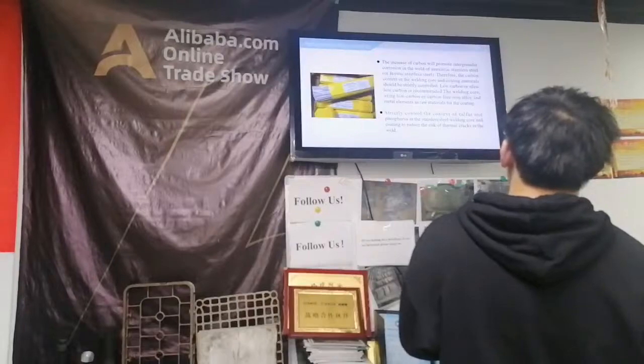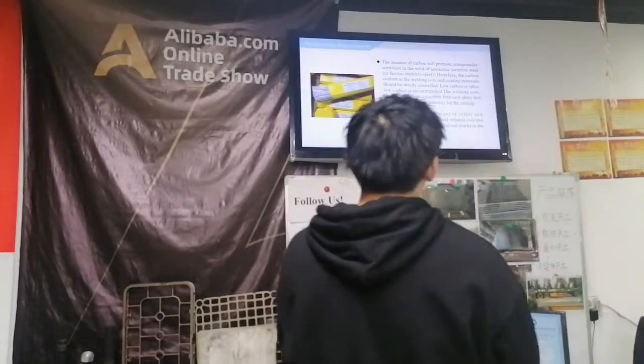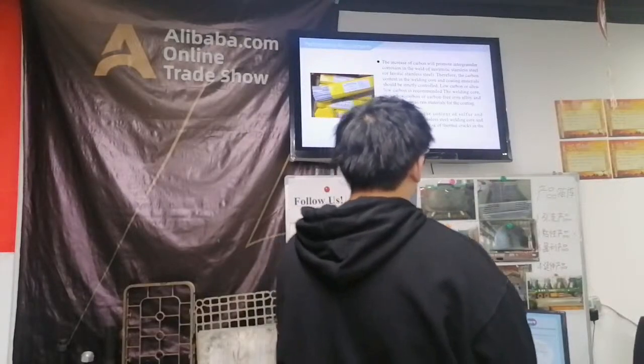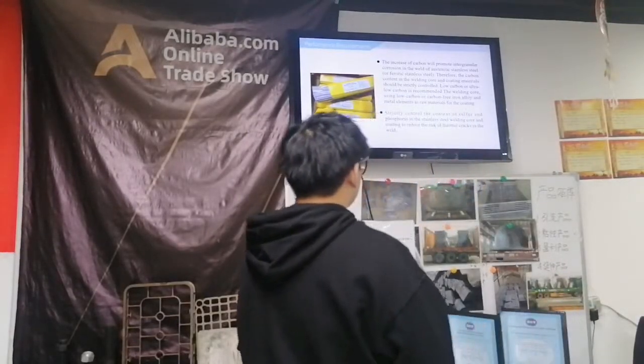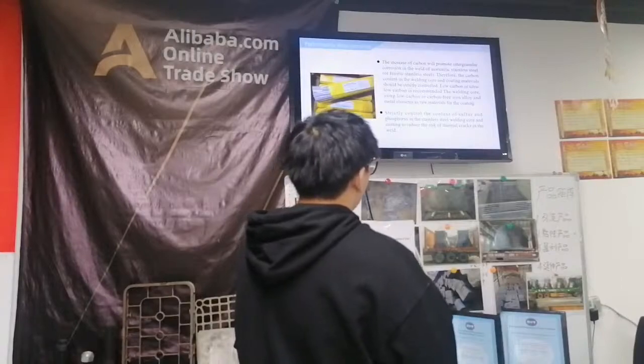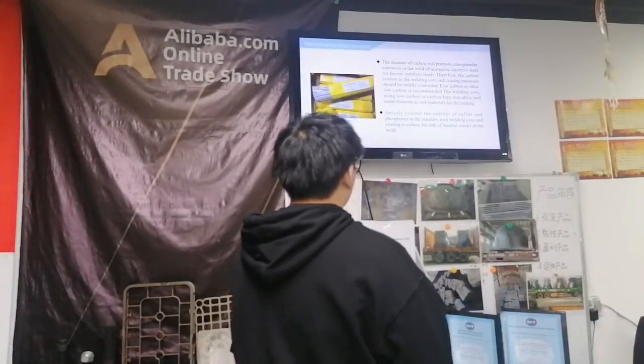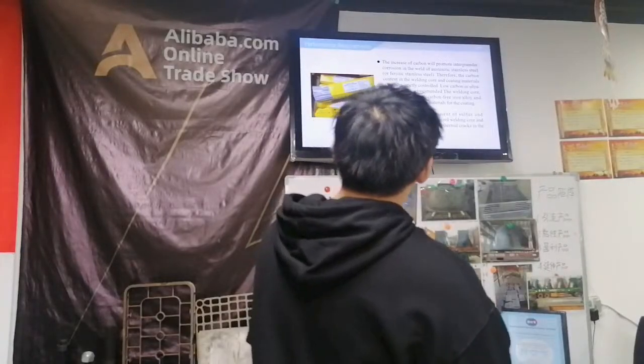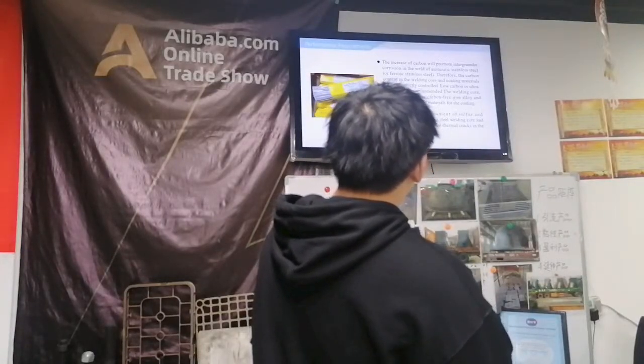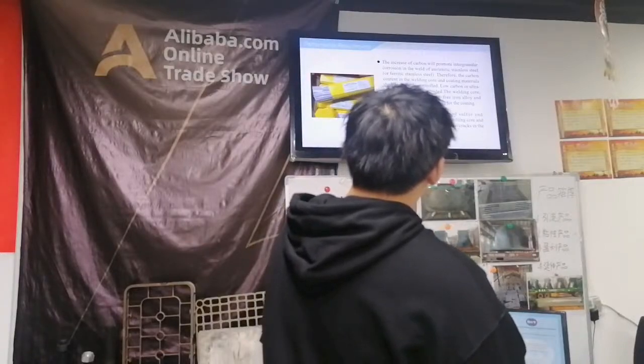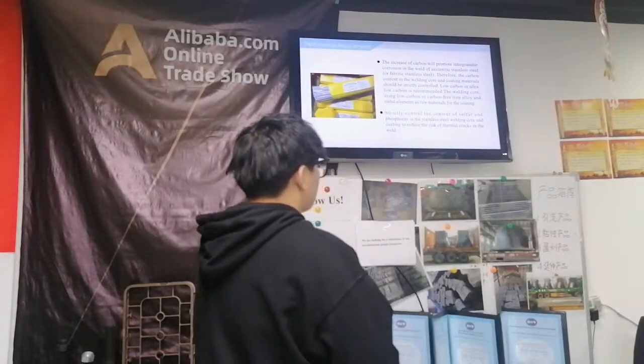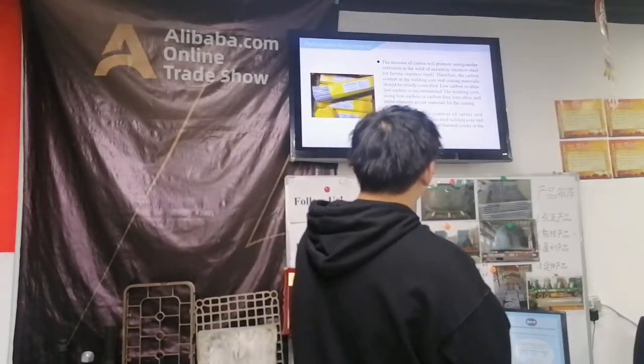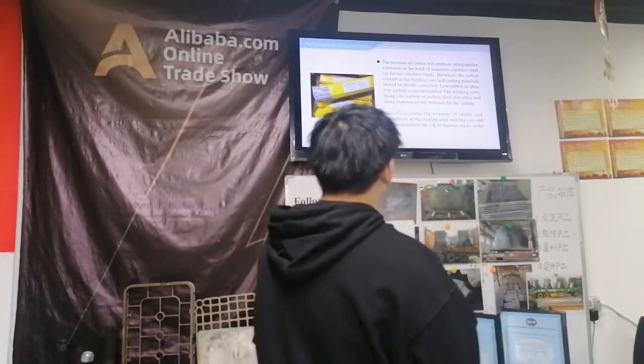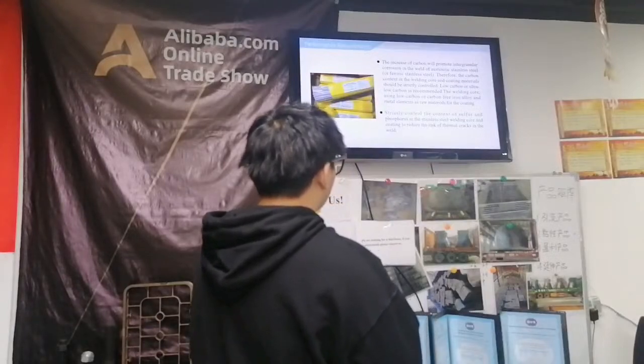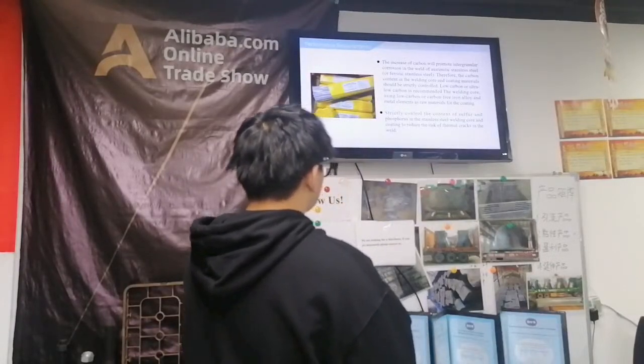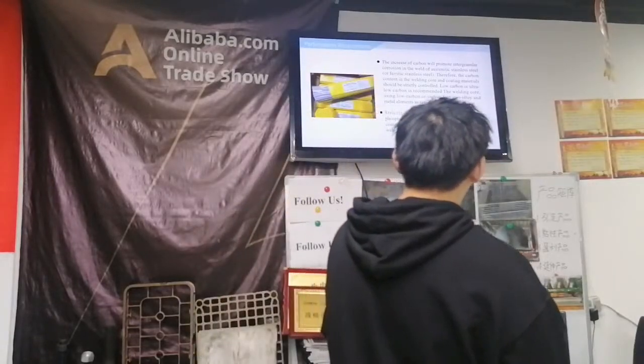intergranular corrosion in the welding of austenitic stainless steel. Therefore, the carbon content in the welding core and the coating material should be strictly controlled. Low carbon or ultra low carbon is recommended in the welding core, using low carbon or carbon-free alloy and metal elements as raw materials for the coating. Strictly control the content of sulfur and phosphorus in the stainless steel welding core and coating to reduce the risk of thermal cracks in the weld.